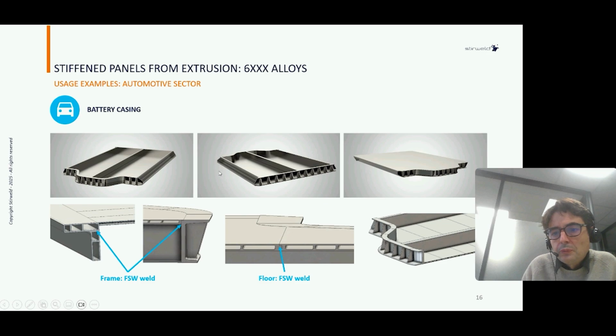So this battery casing is composed of two different parts. The first part is the floor here, and so we start from extrusion, and again we weld by Friction Stir Welding, butt welding this extrusion to compose the floor. And after we will weld a frame onto this floor. So in fact, generally for this kind of application, we have two kinds of weld: butt welding to get the floor, and lap welding to weld the frame onto the floor. And so of course we reverse the battery casing, and we get this casing.